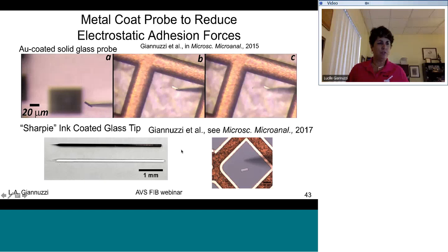So just one other question, people always ask me, why don't we just use a tungsten metal tip? And the answer is, if anybody has accidentally smashed a tungsten probe tip inside of their FIB when trying to do in-situ lift out, they know that the tip will curl up like a little elf shoe. So this will happen too, if you just touch the inside of the trench with the tip. So by using the glass probe, it's stiff, but will flex a little bit and without deforming. So that's why we use the glass probe and just metalize it if necessary.